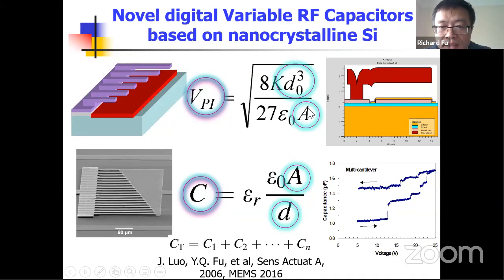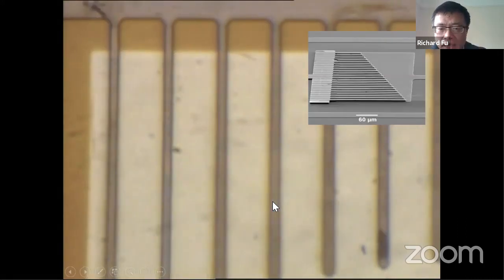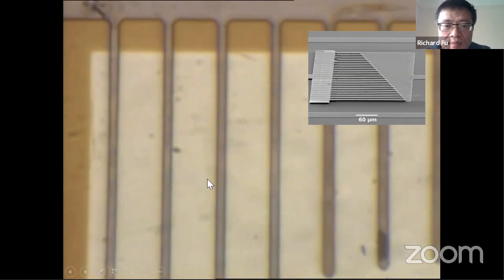That means the longest cantilever has the highest overlapping area, which has the lowest voltage. If you continue to increase the voltage, the shorter cantilevers will be pulled in. Each pull-in produces a jump of the capacitance. So we can digitally increase the capacitance as the fingers touch down one by one. This is a function we can realize using common silicon materials and multiple cantilever designs with different lengths. It really looks like playing the piano, fingers touching down, up and down.